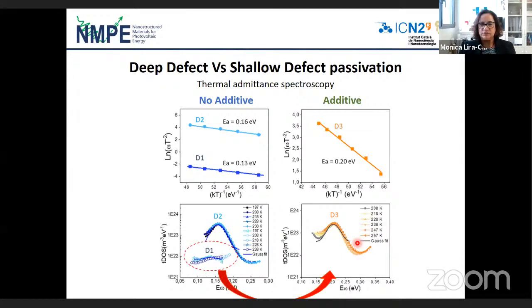So this is what tells us, the no presence of shallow defects in our material with the additive, what finally tells us that what's happening is that we are passivating shallow defects.